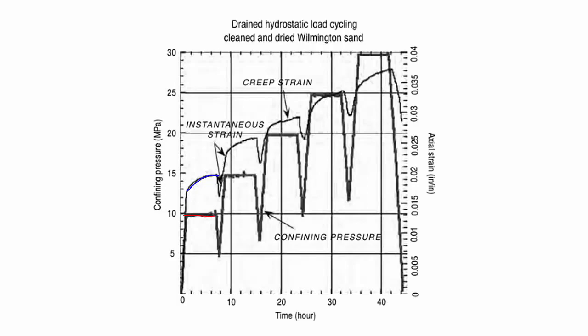Then it was briefly unloaded, reloaded to a higher pressure, and held fixed, and the material strained. This continued through every loading cycle. So that's an example of creep.